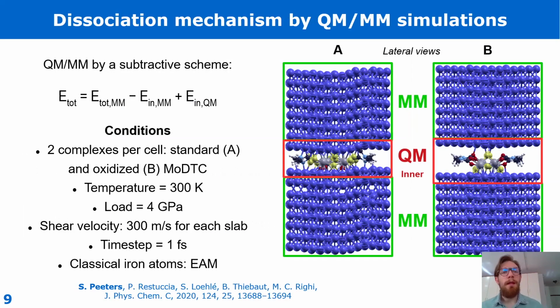To better understand the tribochemistry of MoDTC additives, we designed quantum mechanics molecular mechanics simulations by employing a subtractive scheme. This approach is particularly useful because it allows us to focus the computational power only on the region where chemical reactions take place. In the quantum region, energies and forces are calculated at the DFT level. The rest of the system is treated by classical formulas, which are not typically designed to represent the tribological system in this condition of extreme reactivity.